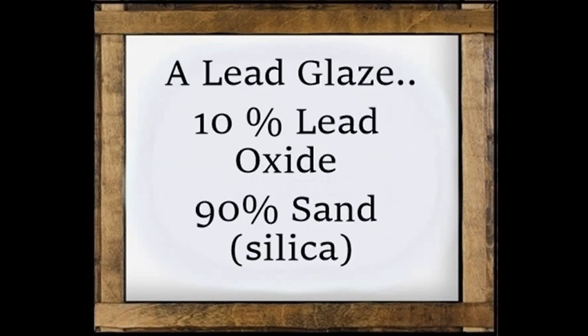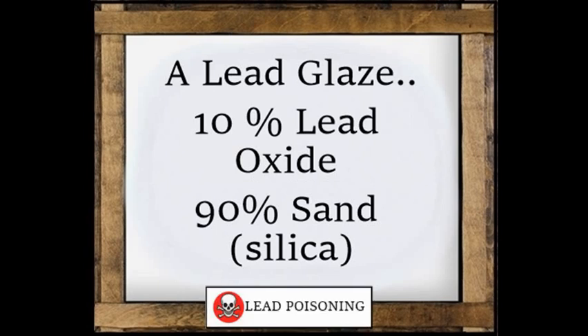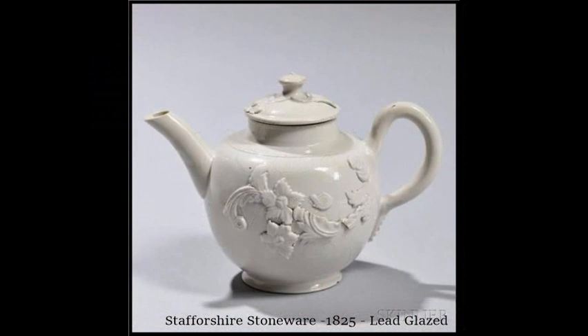Lead glazing was used quite a lot on early English and continental stoneware, when they hadn't yet acquired the knowledge of high-fired feldspathic glazes. A simple recipe might have been 10% of lead oxide and 90% of ordinary sand. The lead acted as a flux to melt the silica to form the clear glass-like glaze. However, it was later discovered that lead could leach out of the glaze into the food or liquid, resulting in lead poisoning. So, lead glazing was eventually banned in the pottery industry. This is a typical Staffordshire stoneware teapot with a basic clear lead glaze finish.